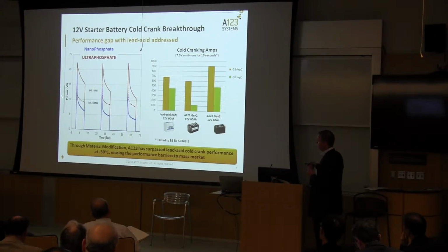What you're really looking at are cold crank pulses. So it's the power as a function of time, and you're looking at different pulses. And then I have two different curves here: the beginning of life, and then at the end of life. And so for our older version of the technology, this was pretty good. But if you actually compared it to the actual lead acid AGM battery, you could see even at -30 degrees C, we couldn't supply the cold cranking amps that are required.